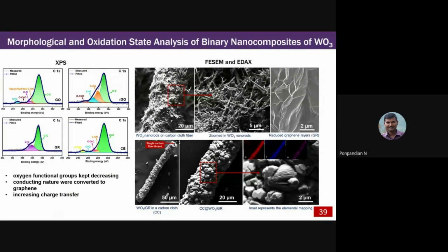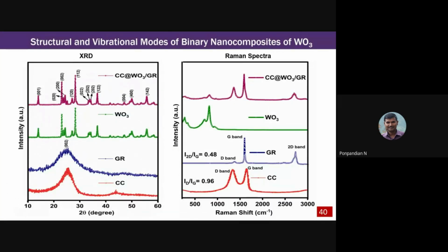Okay, these are some more characterization analyses of this particular binary nanocomposite. This is the graphene together with the tungsten oxide. You can see the rightmost picture. That image is the graphene sheet, and the tungsten oxide is deposited on the graphene sheet. You can see the tungsten oxide together with the graphene. Again, these are the characterizations of these binary nanocomposites, XRD, Raman, and all those analyses. Here you can see the Raman spectrum that shows the graphene. This graphene is already there in this particular composite.